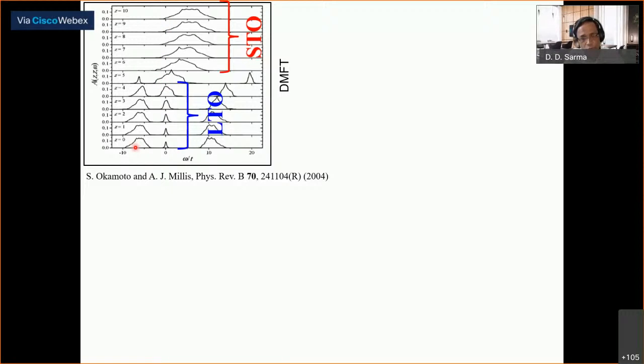And this, what we call the Mott-Hubbard sideband or lower Hubbard band, has very strong intensity for LTO deep inside. But as you approach the interface layer from the LTO side, this Mott-Hubbard intensity goes down and becomes zero by continuously decreasing. So the coherent peak goes up, the incoherent peak goes down in going that direction. And changes happen over many, many layers.